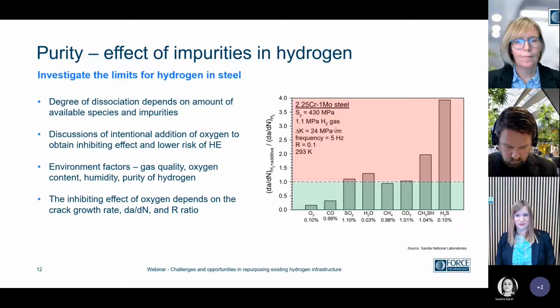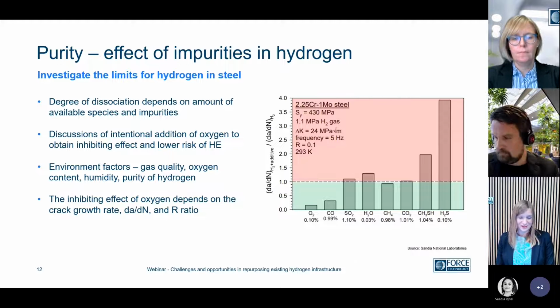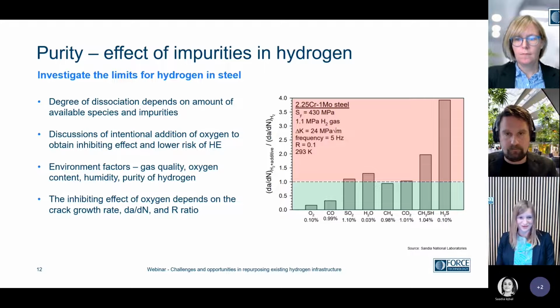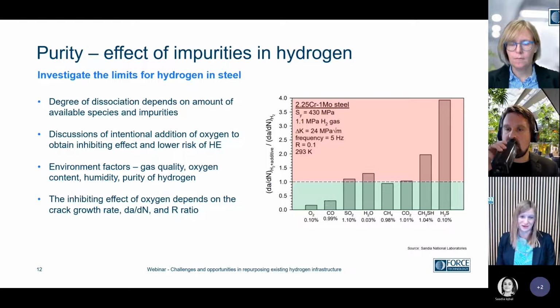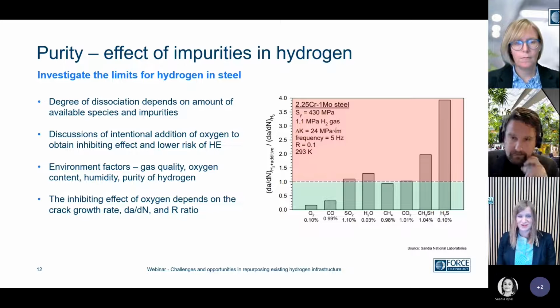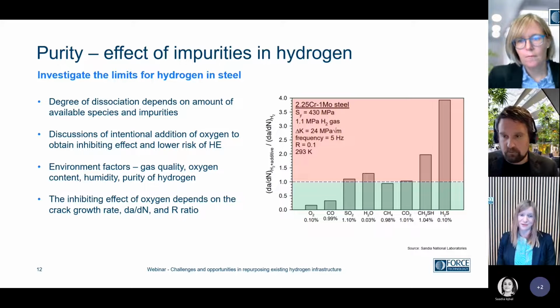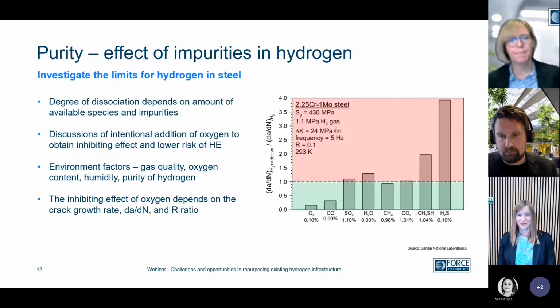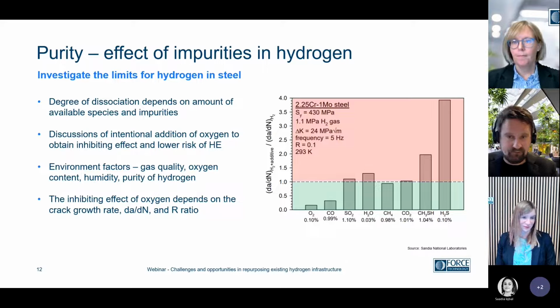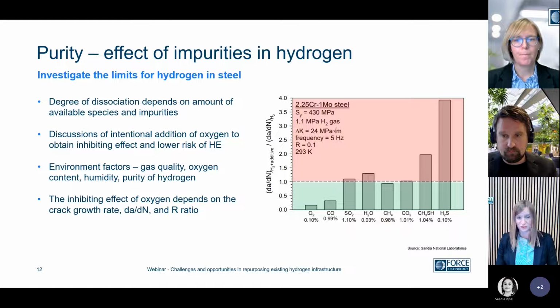And some of these driving forces for hydrogen dissociation include moisture and hydrogen sulfide. As you can see from this plot to the right, all bars in the red area increase the hydrogen uptake as compared to 100% pure hydrogen. So moisture is something to look out for. And we know from oil and gas that hydrogen sulfide accelerates the hydrogen uptake in steel significantly. On the contrary, we have oxygen and carbon monoxide inhibiting or limiting the hydrogen uptake in the steel.